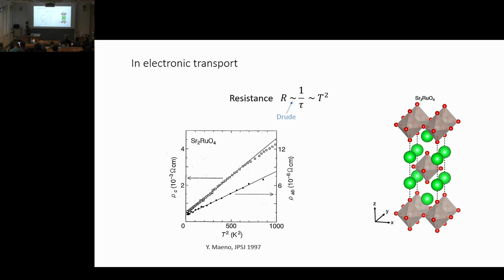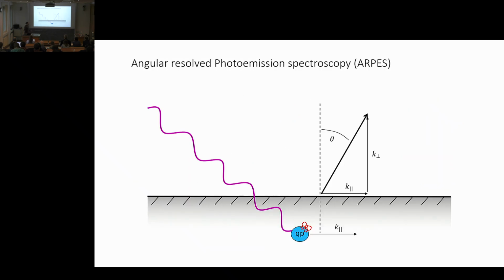law for low temperature. You can see here the x-axis is proportional to T squared, and it's perfectly linear, up to a point which is about 25 Kelvin. Then for warmer temperatures, the Fermi liquid theory breaks apart. But for cold temperatures, it's basically spot on. I'm not doing anything with transport. As Anna already told you, I'm doing ARPES here.